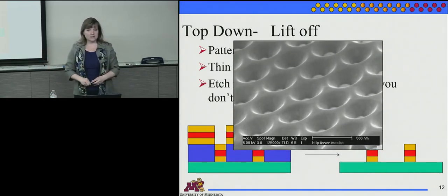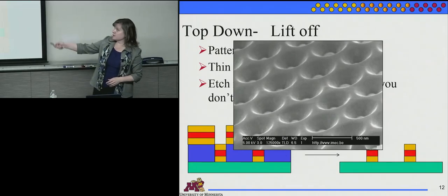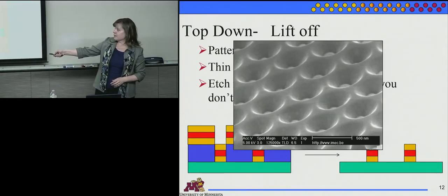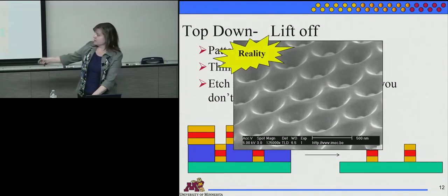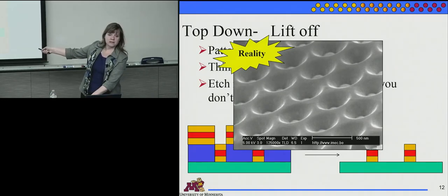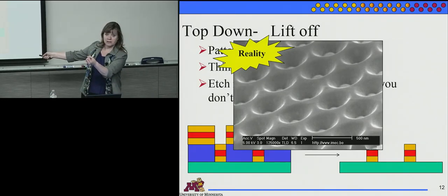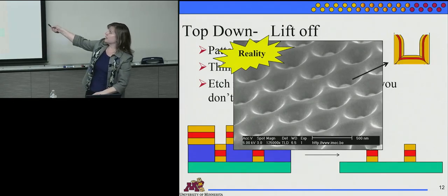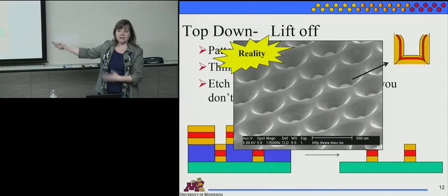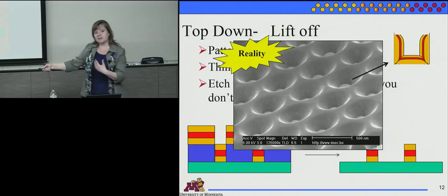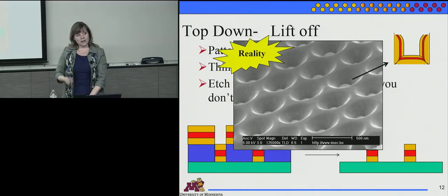But in one case that we had, we patterned nanostructures and we put down films, and it doesn't look like this at all. And that means that your sidewall, if you're relying on this pristine layering, but you want a diameter that's really small, what you might find you actually have in your device looks more like that. And that's going to behave differently than this behaves. So it's just something to be aware of and think, is there a way I could overcome that?